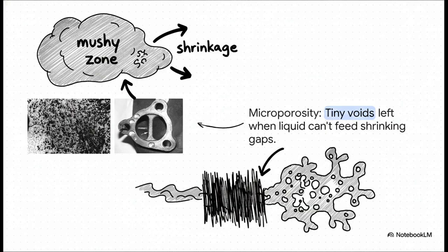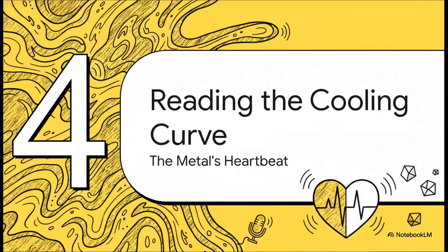When shrinkage wins, it literally rips open tiny little gaps between those interlocking crystal branches. And if that mushy zone is too thick, fresh liquid metal can't get in there to fill those voids. What you're left with is a sponge-like network of microscopic holes, a hidden weakness, born directly from losing that battle. Now, this whole drama is happening in a fraction of a second, deep inside a glowing, molten liquid.